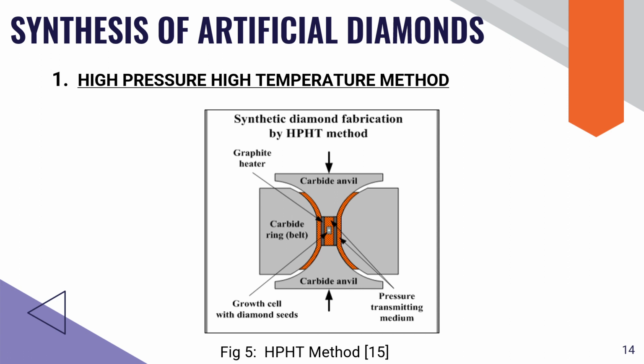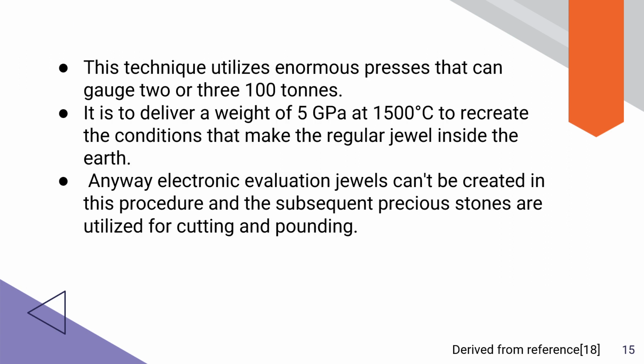The high pressure, high temperature approach produces conditions for diamond growth that are similar to those found in nature. A growing cell that is equally pressured and filled with molten metal like iron, cobalt and nickel that has carbon atoms dissolved in it is used to generate tiny diamond seeds. Carbon atoms accumulate on the surface of the seed due to the high temperature of about 1300 to 1500 degrees Celsius and a high pressure of 5 to 5.5 GPa.